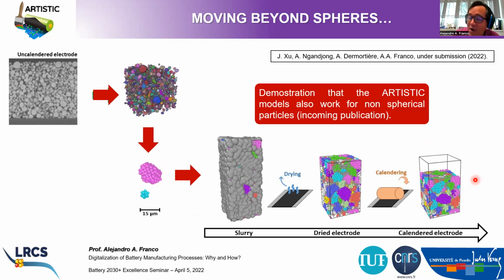So we believe this is also a step forward towards this digital twin of the manufacturing process, because now we are able to take into account real particle shapes, right? And not only spheres. Even though with spheres we can get satisfactory results, right? And we can get good predictions anyway, right? The take home message here is that you don't have to complexify the model if it's not needed, right? But here we want to do it just for fun, right? Just because, okay, are we capable with this workflow to simulate the manufacturing process with real particle shape? The answer is yes, right? And this is a paper that is now currently under submission, right?